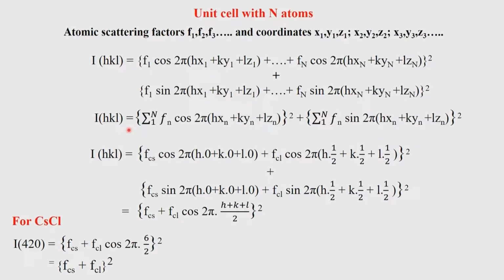We will now take up a discussion on the structure factor, but before we go into the detail of the structure factors associated with any diffraction condition, which is an important factor, remember we had two expressions. We called them Fourier transforms of each other. We showed that F of HKL is related by a Fourier transform to rho of r, where rho of r is the electron density, and vice versa. That is, from rho of r we can get to F of HKL.